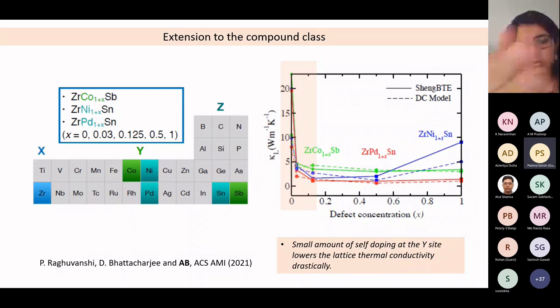So we took into account different compositional space, keeping the 18 valence electron count in mind. And we saw that indeed, in most of these materials, the full Heusler compounds have lattice thermal conductivity as high as 10 to 20 at least. But the moment there is a little bit of substitution at this Y site, the lattice thermal conductivity drops drastically. And these are very accurate calculations taking into account all the anharmonic effects and everything possible.